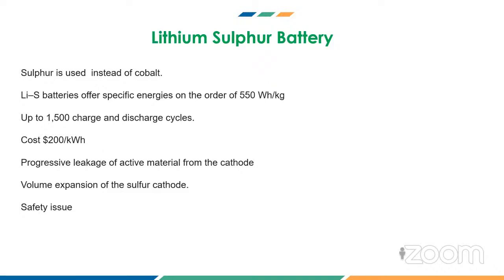So the lithium sulfur battery's biggest advantage is this about 550 watt-hours per kg. 550 means nearly 3 to 4 times when compared to lithium iron phosphate or lithium manganese oxide, whatever it may be. And at the same time, life cycle is also very high, about 1,500 cycles. Cost wise it is cheap, but it has some unwanted problems too. Still it is under development stage, it is not yet commercialized.